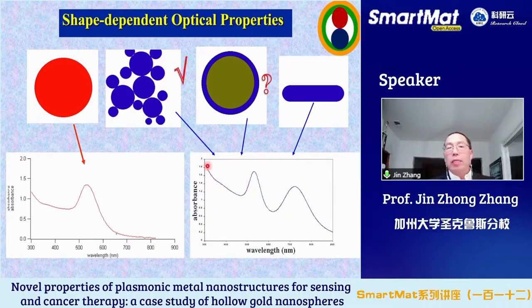However, in the reaction I just talked about, it's not nanorods, it's not a core shell. Instead, after over 2 years of research, it's aggregates. The aggregates can form sort of a long axis this way, if the electrical field of light is along this axis, or transverse like that. And it turns out there are many papers on aggregates of gold and silver nanoparticles, and they have exactly the two peaks we observed.